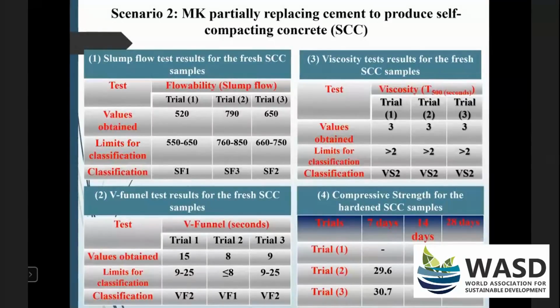For the second scenario, incorporating metakaolin to partially replace cement to produce self-compacting concrete, three mix trials were conducted, where the first trial was not successful, and for the second and third trials, we were able to get self-compacting concrete. We had the fresh concrete tests for the slump flow, the V-funnel test, and the viscosity test, as well as the hardened concrete properties, where we checked the compressive strength.